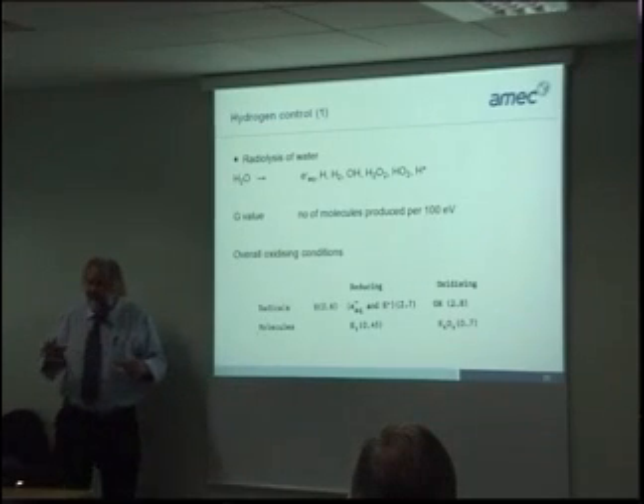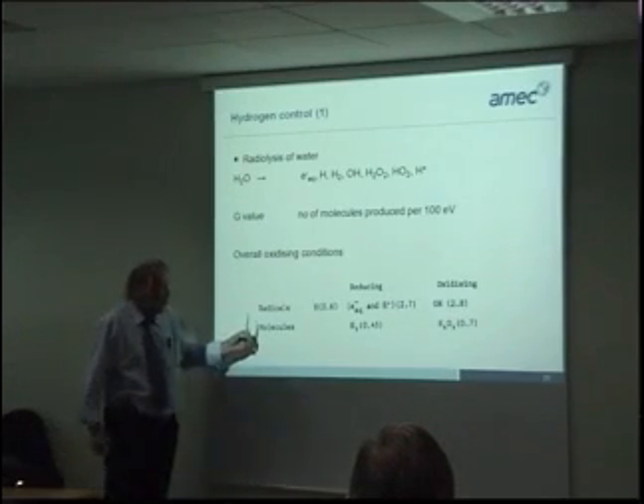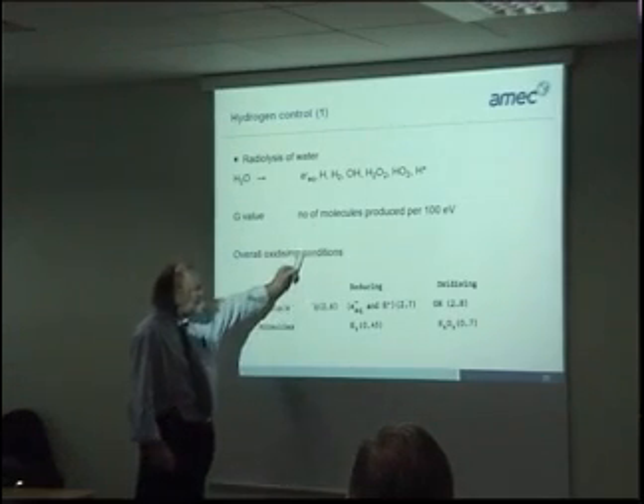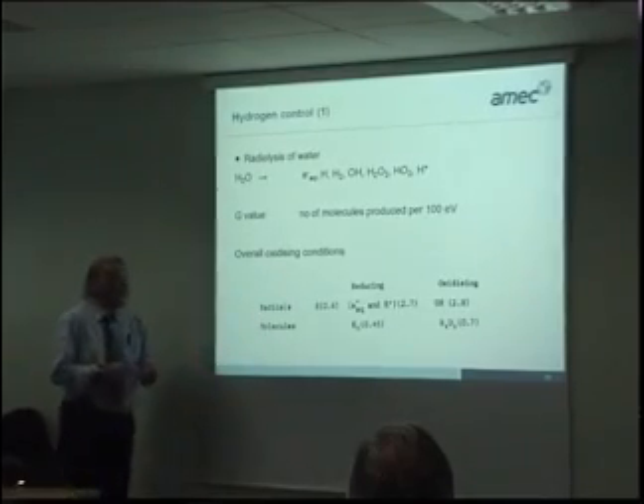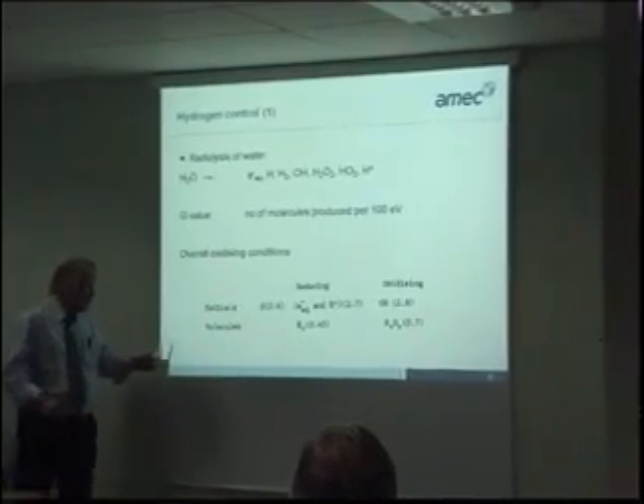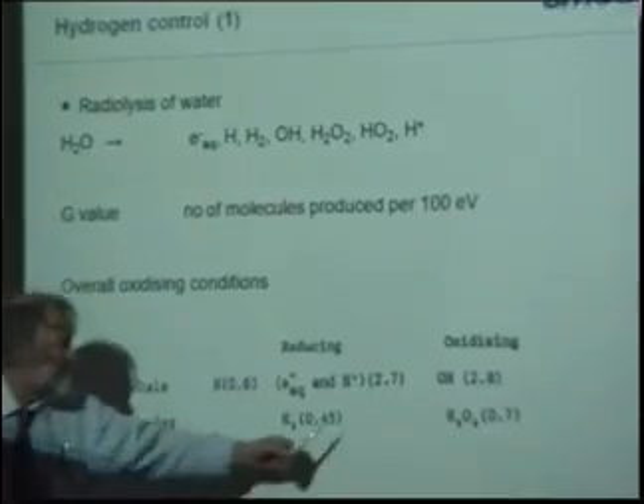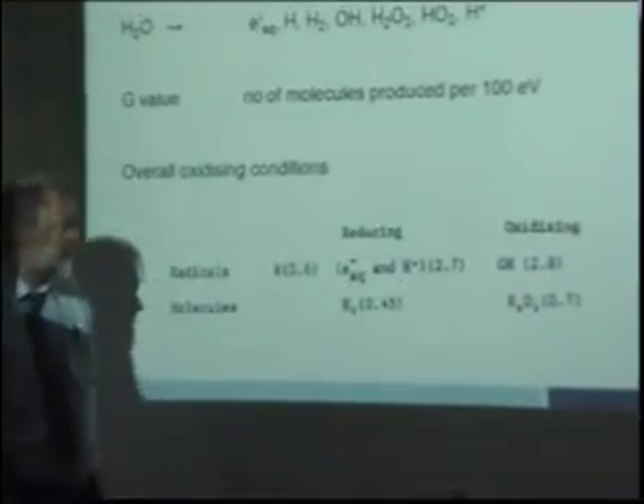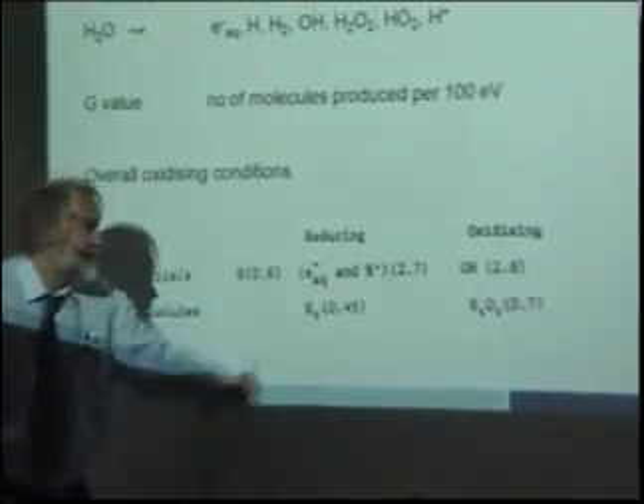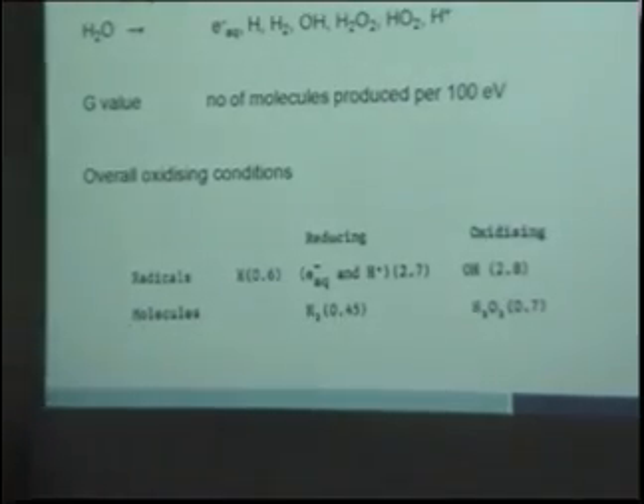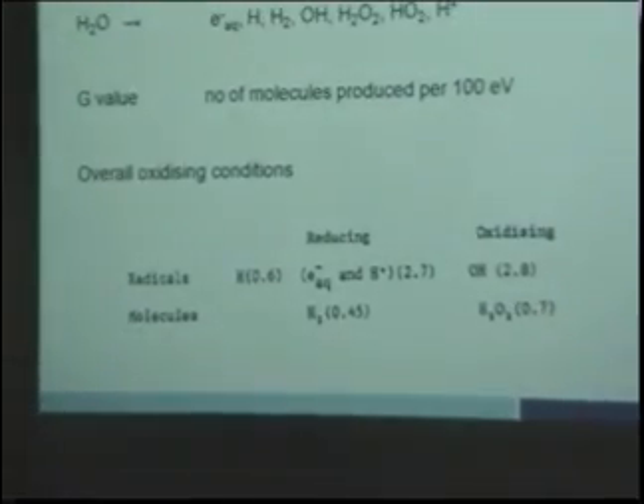I don't know whether any of you are familiar with the radiochemistry. We use G values, which is the number of molecules produced per 100 electron volts absorbed, and we find that oxidizing species are about 2.8 and reducing at 2.7. Now, the oxidizing species, of course, are going to do a fair amount of damage to the steel in contact, or the metals and alloys in contact. So we mitigate that by dosing with hydrogen.